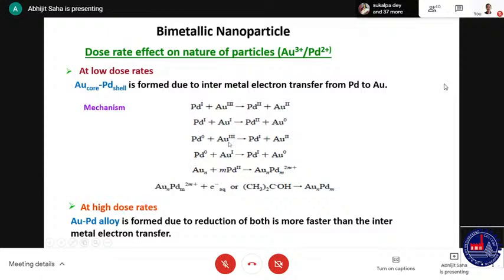You can also develop bimetallic nanoparticles. Suppose you have one metal particle, then you can combine it with another metal. That is what's called bimetallic materials. For example, gold and palladium. Gold is inside the core, and the shell is made by palladium. This is formed due to intermetal electron transfer from palladium to gold. So this is a standard reaction process where you can get a gold-palladium core-shell structure.